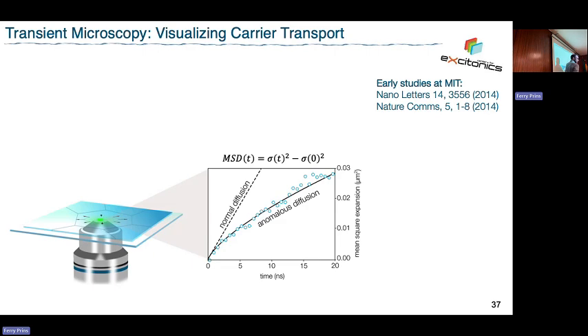Most cases, what we see is, well, we almost never see a straight line. We almost always see something that slows down. The slope gets smaller and smaller - fast in the beginning, but slower later on.